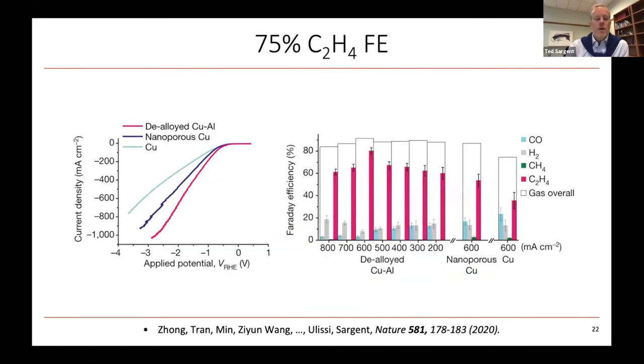And what we found was that relative to pure copper or nanoporous copper, which has a Faradaic efficiency of typically 60 to 65%, we were able to achieve at very high current densities. You see here we're at about 600 milliamps, which is getting close to that amp range you really want to be in. We're able to get to 75% on average and the occasional 80% Faradaic efficiency with these optimally designed aluminum-coated copper surfaces in these nanostructured systems.